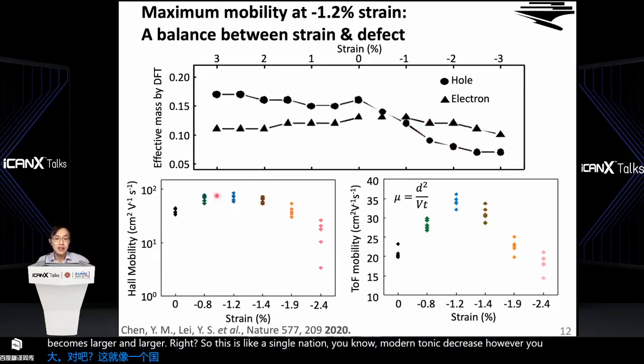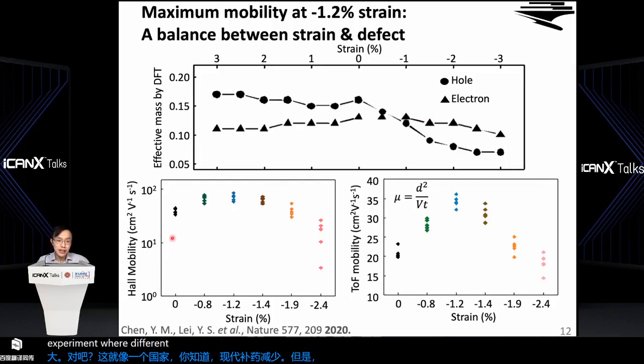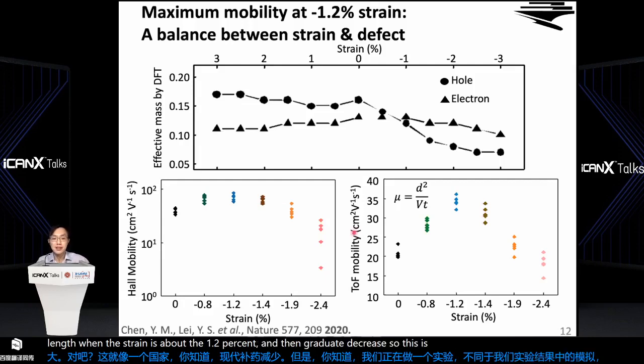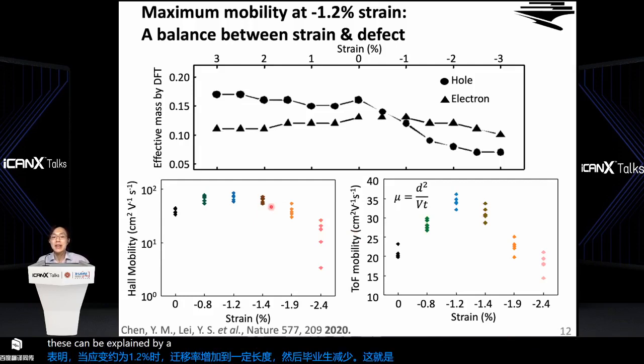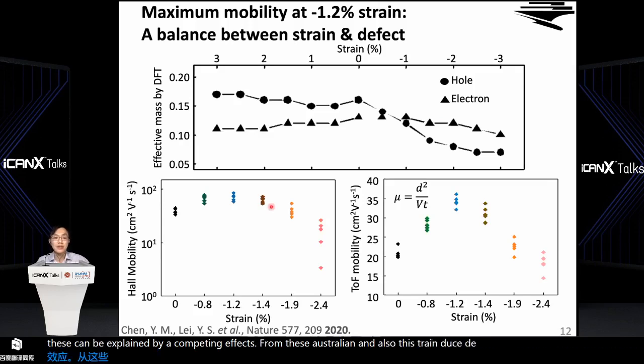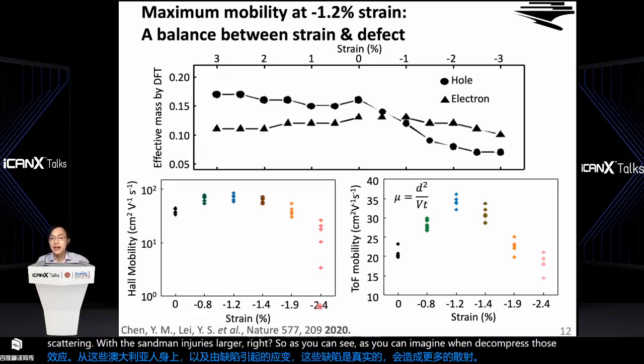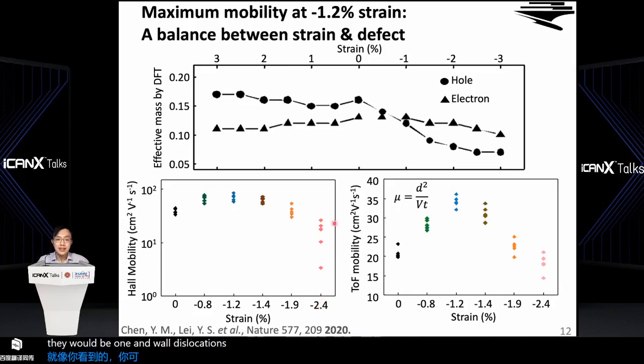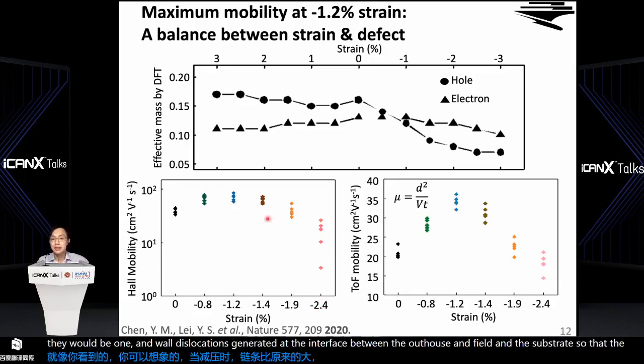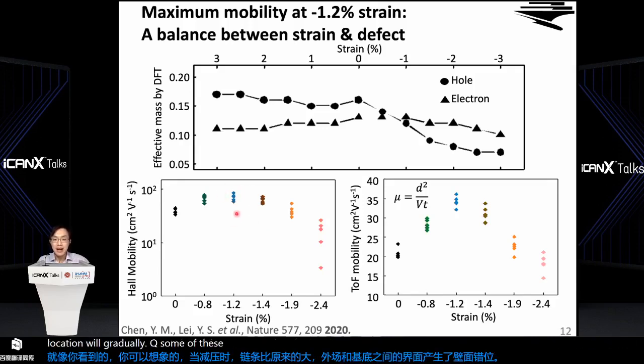However, our experiment is very different from this simulation. In our experiment, the result shows that the mobility gradually increases to a certain amount when the strain is about 1.2%, and then gradually decreases. And this can be explained by a competing effect from the strain enhancement and also the strain-induced defects that will create more scattering when the strain magnitude is larger, right? As you can imagine, when the compressive strain is larger, there will be more and more dislocations generated at the interface between the epitaxial thin film and the substrate. So those dislocations will gradually kill some of the carrier transport. That's why we have a maximum value, a sweet spot at around 1.2%.